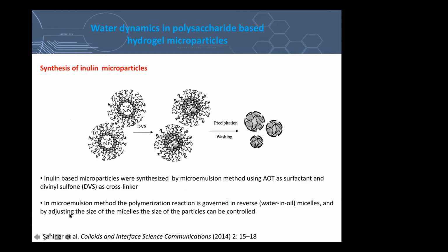So, if I should mention the synthesis, the inulin-based microparticles were synthesized by the microemulsion method. In this method, AOT is used as a surfactant. As you can see here, the hydrophilic parts look at the center, and the hydrophobic parts are oriented outwards, building the water-in-oil micelles. In this case, the polymerization reaction takes place inside these micro-sized micelles. So by adjusting the size of the micelles, it is also possible to tune and control the size of the particles.